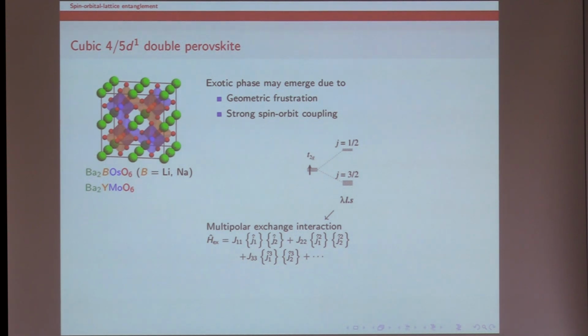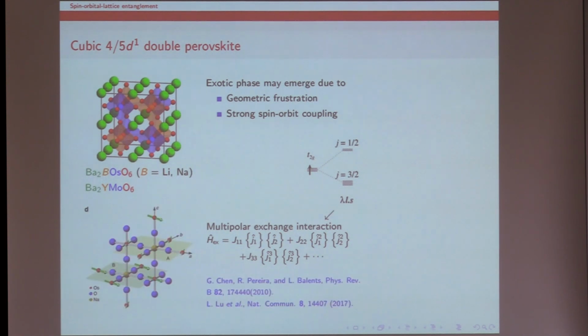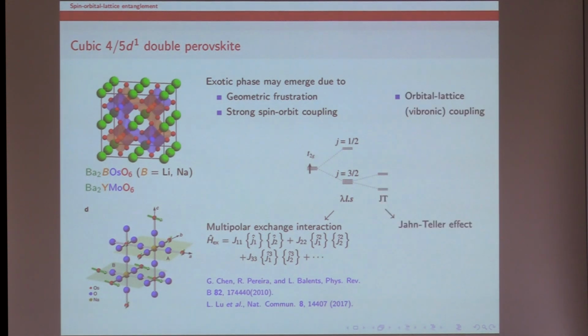And in the case of ordered systems, they have been studied by mean field theory and so on, and canted antiferromagnetic order has been predicted, and then later it was confirmed experimentally. And in such a system, because of high degeneracy, orbital lattice coupling can survive. And in this case, the Jahn-Teller effect may appear. However, this effect hasn't been investigated in this system much.